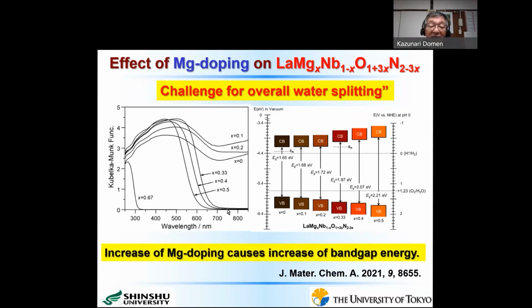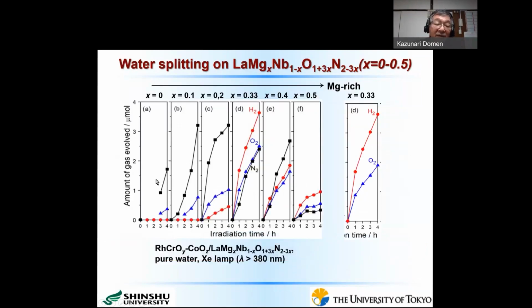Then we examined these materials' activity for the overall water splitting reaction. In this particular case, our system had some leakage of air, so we observed some nitrogen and oxygen leakage, unfortunately. But please focus your attention on these red curves. This is the hydrogen evolution activity. As you see here, when we reached X equals 0.2, we started to observe hydrogen evolution. And when we reached X equals 0.33, or X equals 1/3, the hydrogen evolution activity becomes much better. However, when we increase the dopant amount of magnesium further, the activity gradually decreases.